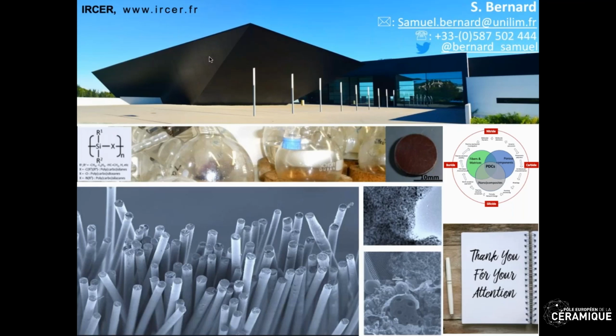I mean, you can even produce near net shape PDCs by the mixture between metallic powders or nanopowders and your pre-ceramic polymers. It is the solution and the only way to control the volume shrinkage occurring during the transformation of your polymer into ceramics. And I have samples. I can send papers.